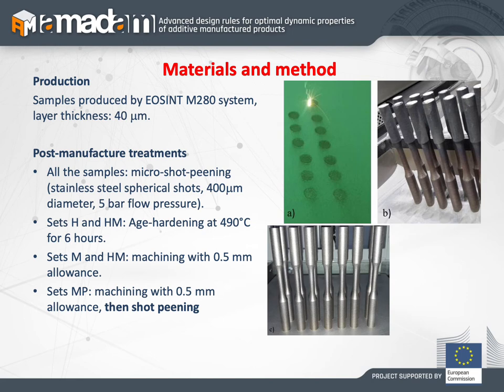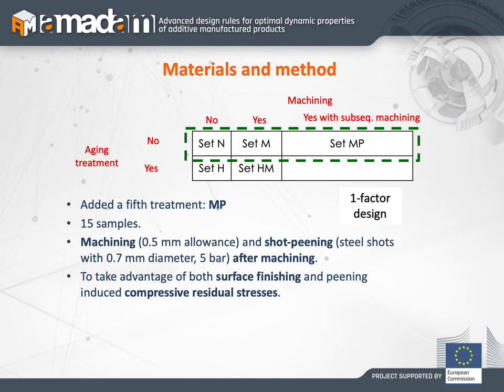And finally, as I have shown you in the previous slide, the set MP means that we have machined the specimen with 0.5 millimeter of allowance and then shot peened it. And therefore it is important to highlight the differences between having machined the specimen after the micro shot peening, or applying the micro shot peening after the machining of the specimen.